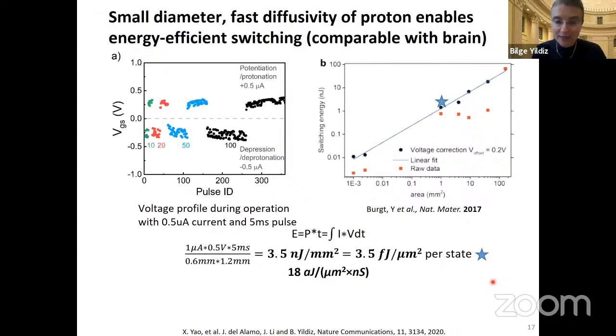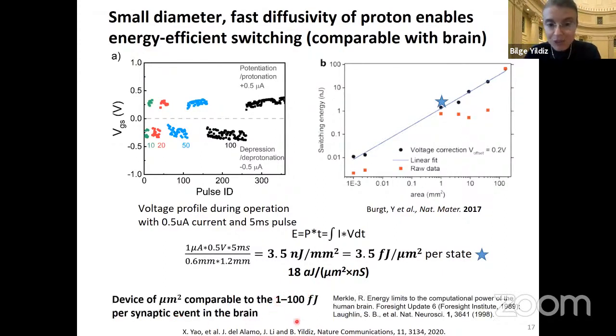and despite that, we have obtained a very low energy consumption per processed state with this system. So here I'm showing the resulting gate voltages that result from the gate pulses of currents that we send. And using this voltage-current data, we could compute the energy consumption per unit area per state. And that comes to about 3.5 femtojoules per square micrometer device per state change. And if you convert that to per unit change in conductivity, it becomes nearly 20 attojoules per square micrometer per nanosiemens.